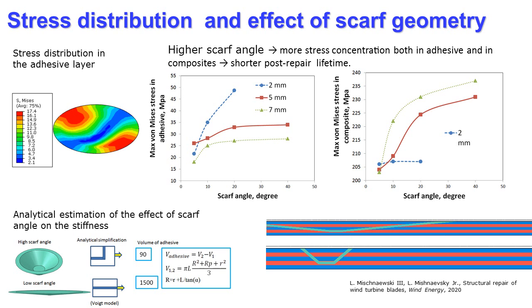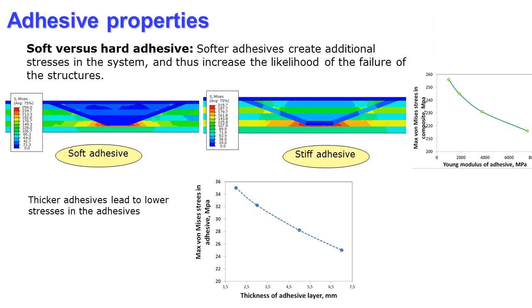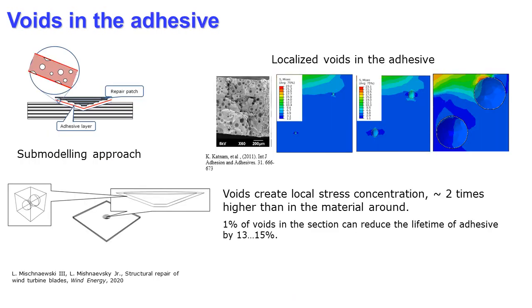A number of computational studies were carried out. One observation is that the most dangerous area in the adhesive is close to the upper part, the coating. Further, we studied the effect of the adhesive thickness and scarf angle. It was observed that a higher scarf angle leads to higher stress concentration both in the adhesive and in the repaired composite. The model was validated by comparison with a simplified analytical Voigt-type model. The computational studies also demonstrated that soft adhesives create additional stresses in the system, as compared to stiff adhesives.